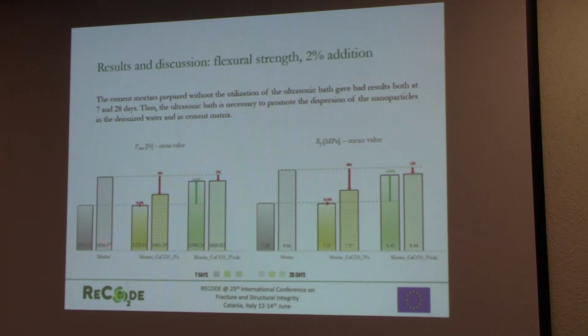And as you can see, in the histogram, we have indicated with gray the reference mortar, with the yellow color the mortar with 2% of calcium carbonate nanoparticles without using the ultrasonic bath, and in green the composition with 2% of nanoparticles mixed in water by means of the ultrasonic bath. As you can see, the cement mortar prepared without the utilization of the ultrasonic bath gave bad results, both at 7 and at 28 days.